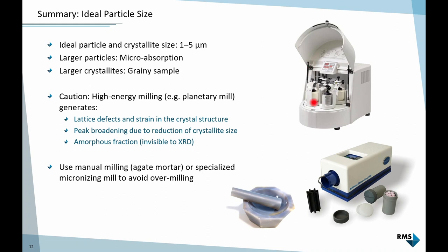But you can also mill too much. High energy mills, especially planetary mills, use very high intensity milling and can destroy your crystal structures. You can introduce defects, lattice strain, and start forming amorphous phase. Usually manual milling in the mortar is time consuming but doesn't over-mill. The McCrone micronizing mill has become an industry standard because it's well suited to reach this ideal particle range without over-milling. It's nowadays sold by Retsch or some of the big mill manufacturers.